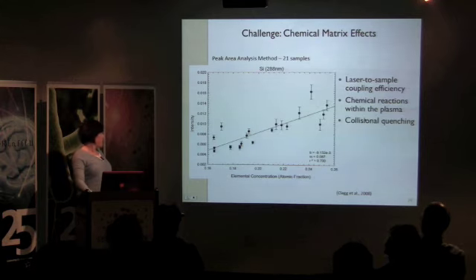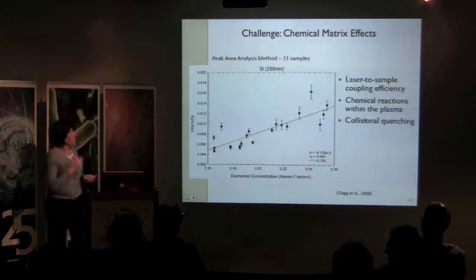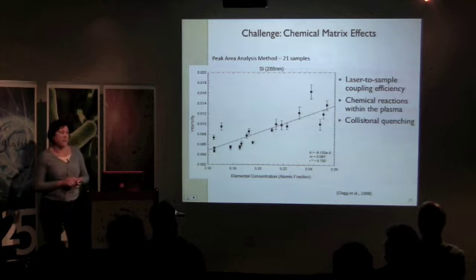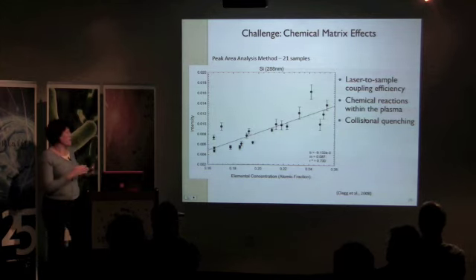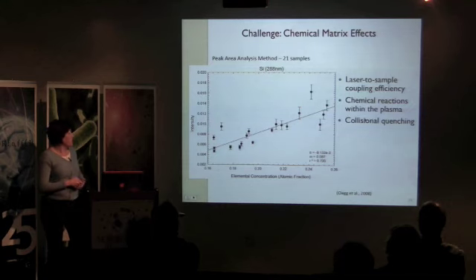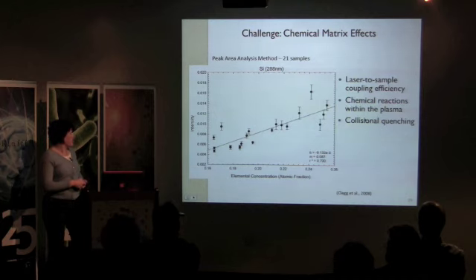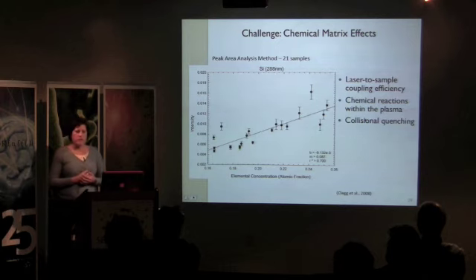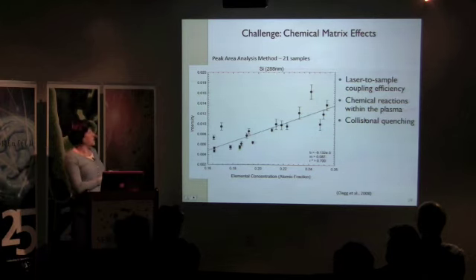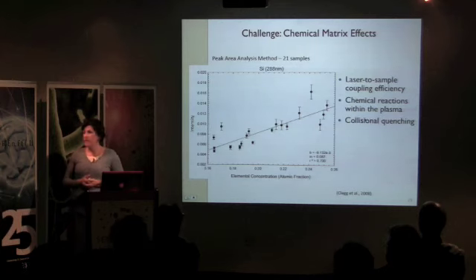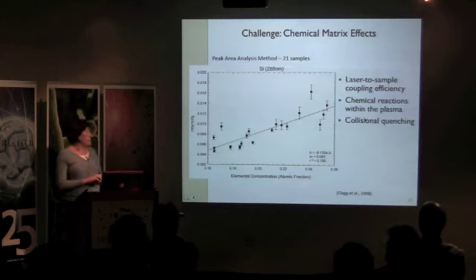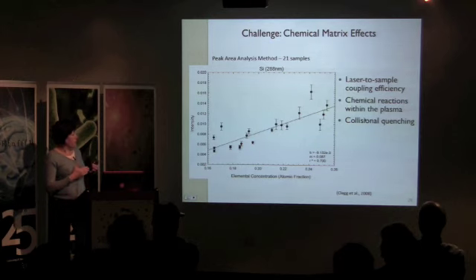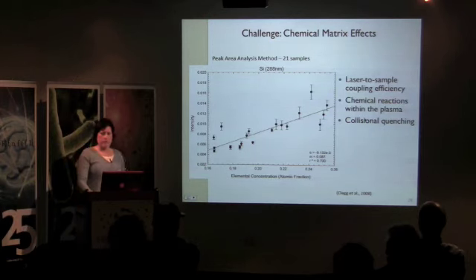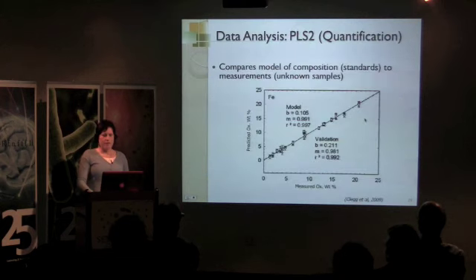All right, so here's another summary sample showing for silicon some challenges associated with matrix effects. This is a summary of 21 samples that were analyzed, and you'd think there'd be a direct correlation right on that line between the intensity and the element concentration, but in fact we see a bit of a scatter. We aren't quite sure what's causing the scatter, but we think it's a contribution of these things: laser to sample coupling efficiency, maybe chemical reactions within the plasma, or maybe even collisional quenching. So overall it's pretty good, but there is still this scatter that reduces our accuracy.